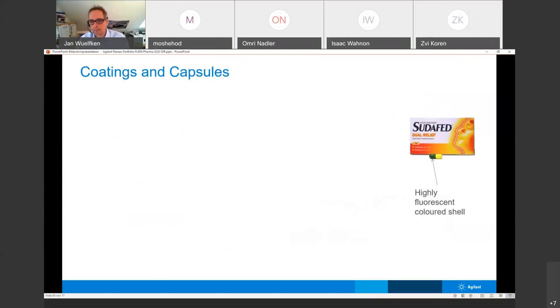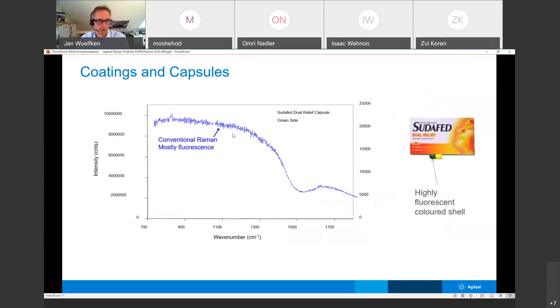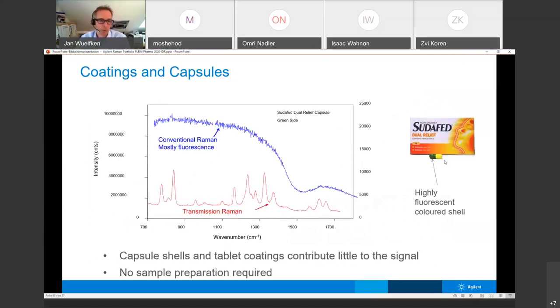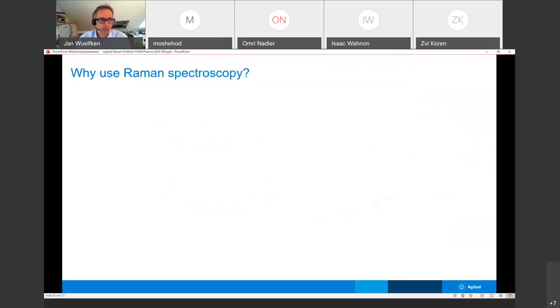Just an example, Sudafed, which has a highly fluorescent color shell here, and paracetamol inside. This is what you get with a conventional Raman. It's mainly fluorescence from the fluorescent color shell. And this is what you get from the transmission Raman. So we can see inside, a bit similar to the raw material, but we're doing something completely different because we use this for content uniformity and also for concentration of APIs.